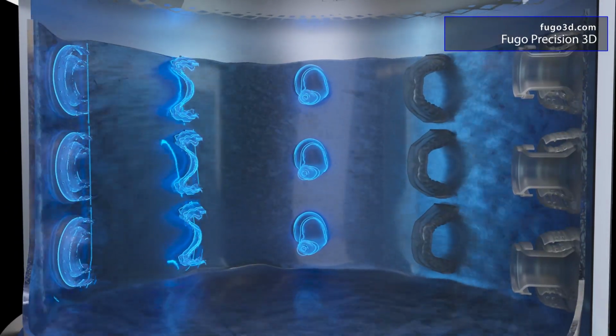Now, this is a very unique approach to additive with many advantages, including the speed is impressive. Less than 1 hour per vertical inch of part, where vertical is actually the axial dimension in the machine. There are virtually no support structures needed because at 3,000 RPM, the resin is pulling 2,100 Gs, which makes it behave like a solid. After the build, the uncured resin simply drains to the bottom for recovery and reuse. The process is not bound by the usual limits on photopolymer viscosity, and it can be used with filled materials. Also, there's no mechanical moving parts that can wear or fail.